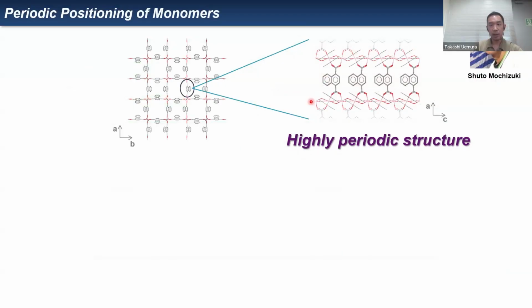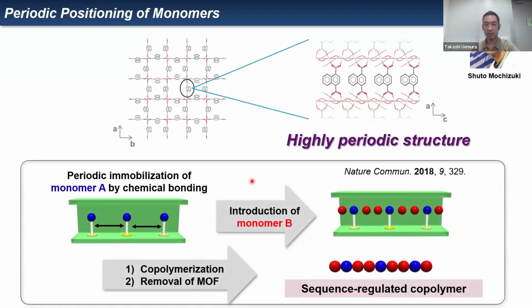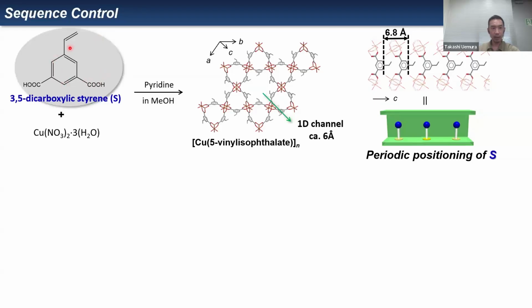Okay, let me show you our strategy to achieve controlled copolymerization using MOFs. As you already noticed, MOFs have highly periodic structures because of their crystalline nature. So if we can immobilize a monomer periodically by chemical bonding, we can introduce another monomer between them at regular intervals, so that we perform the copolymerization between them to give the sequence-regulated copolymers shown here. So here we employ this type of monomer, a vinyl monomer with the functional group, I mean the two carboxylic groups here, to mix with the copper to give this MOF compound.